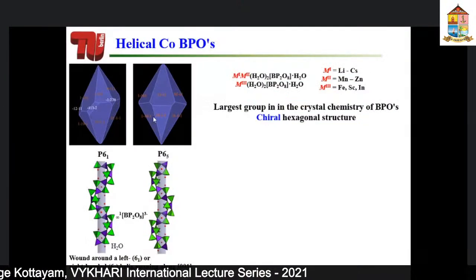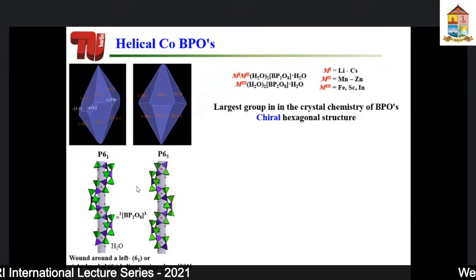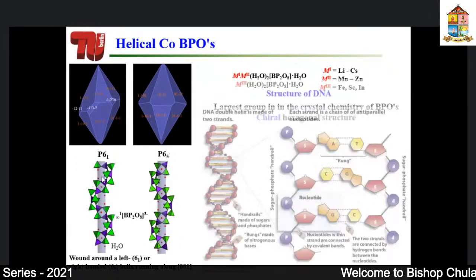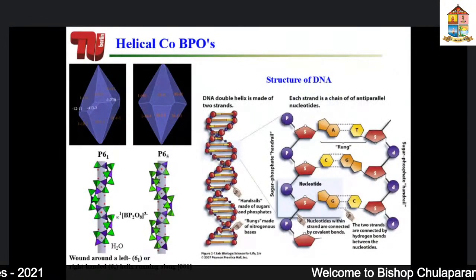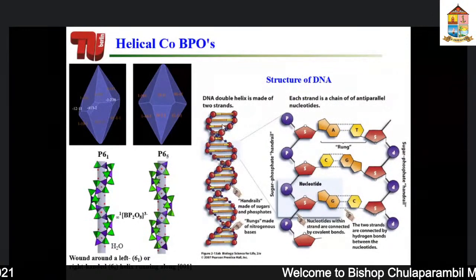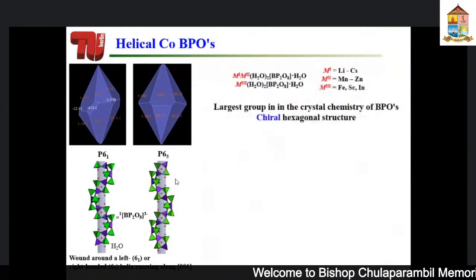So we synthesized a large class of borophosphate compounds, which are called helical borophosphates. As you would see, they look like hexagonal bipyramids morphologically, and they have a very nice structure. You could see that the boron and phosphate tetrahedra are connected together in a wound round left or right-handed helix, which is the crystallographic axis. And then we have water channels inside this kind of chains. If you look very carefully, you would see that they're also very similar to the structure of DNA, where DNA has a double strand structure. However, these are not biologically motivated, so I would just show you the whole structure.